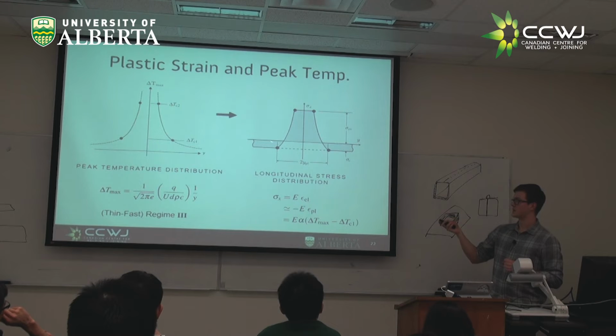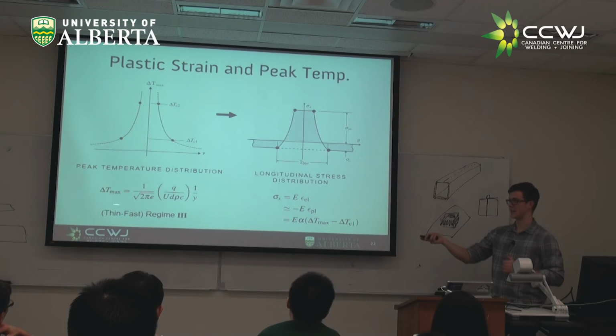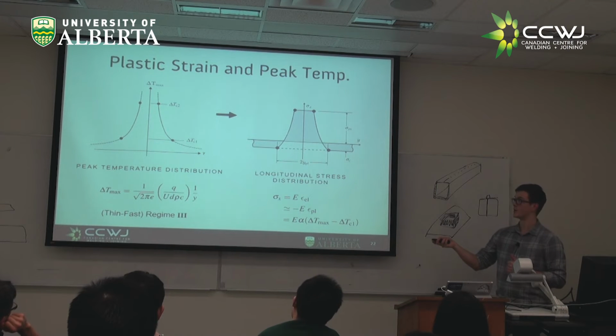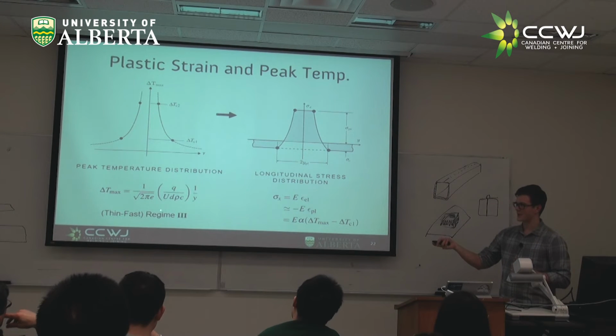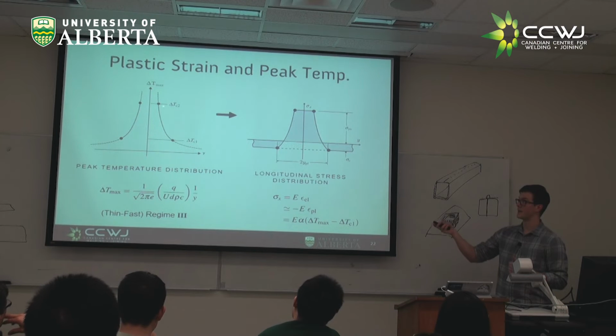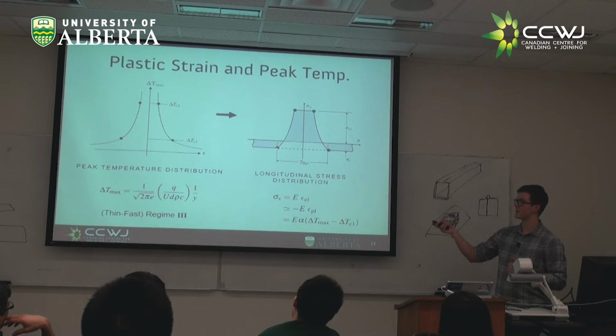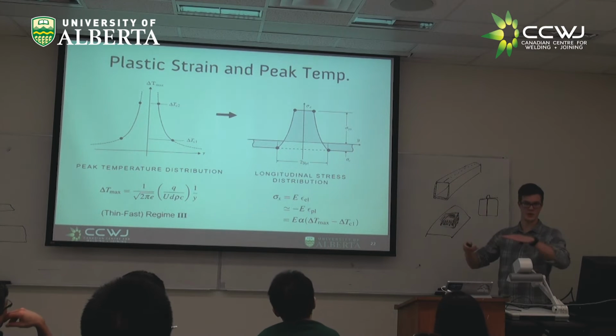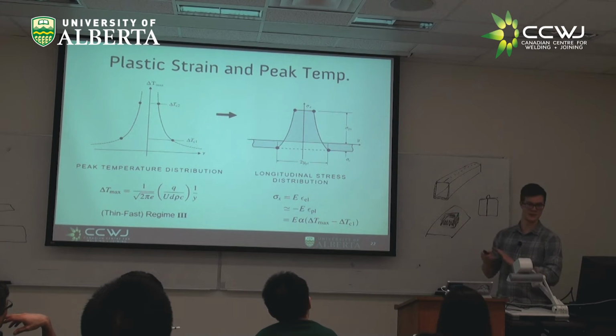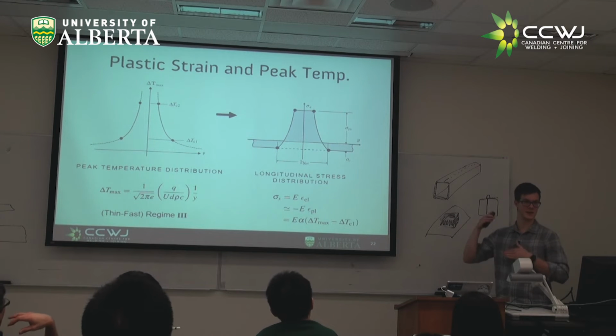So if we look at this stress distribution, we can say, as we said, we have some maximum temperature. We've got some material properties here. This is exactly what we have in our notes from the thin fast regime 3 for the maximum temperature. But really, we don't have to worry so much about all this as we see this inverse shape. That shape here is going to be the same shape as our residual stress distribution. And if we look at this delta Tc1, that's going to be the bound of where we have this block. And delta Tc2 is going to be where we chop it off and we truncate it. And everything above that, we're going to say the stress doesn't increase any higher because we've hit yield.